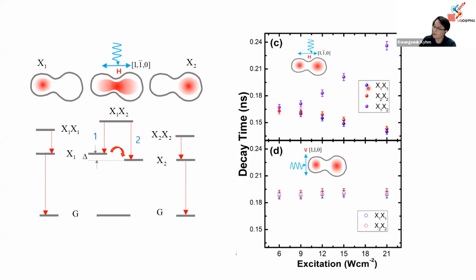Again, we check the local biexcitons 1,1 and 2,2, and compare with the coupled biexciton 1,2. Here, by the way, from X1,2, there is an energy transfer here. But between the two local biexcitons, there is no such thing. So those two, X11 and 22, simply decrease the decay time with increasing excitation.